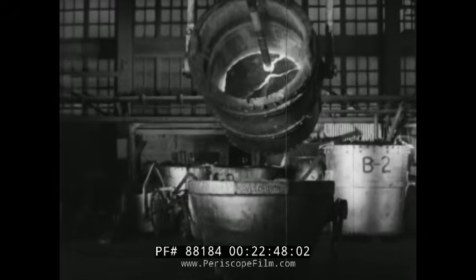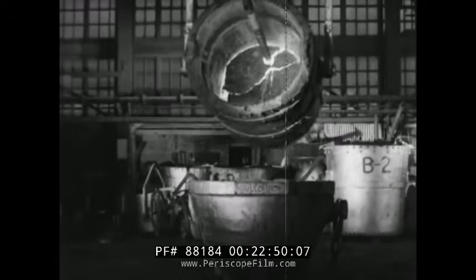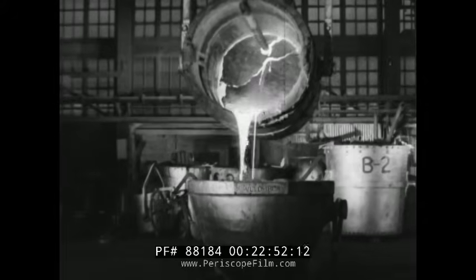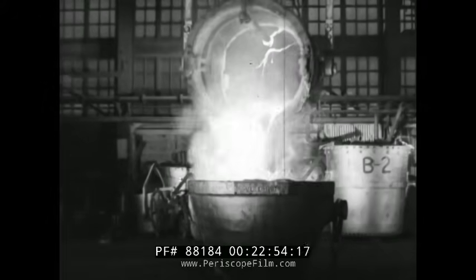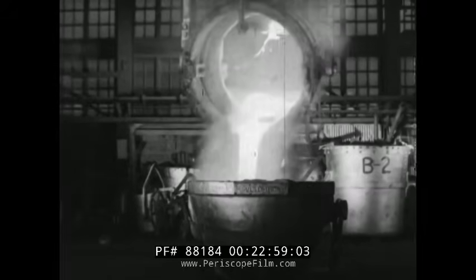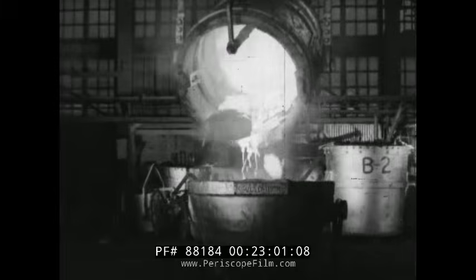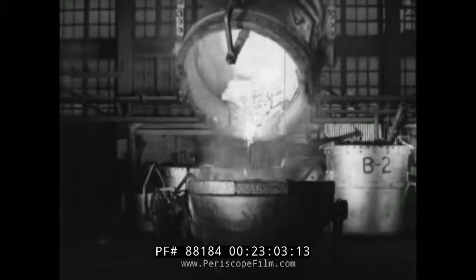When the ladle has finished pouring ingots, there is always a skull of slag and metal left in the bottom. This is removed by dumping into a slag pot. The metal is later reclaimed from the slag. The ladle goes away to be made ready for another heat.